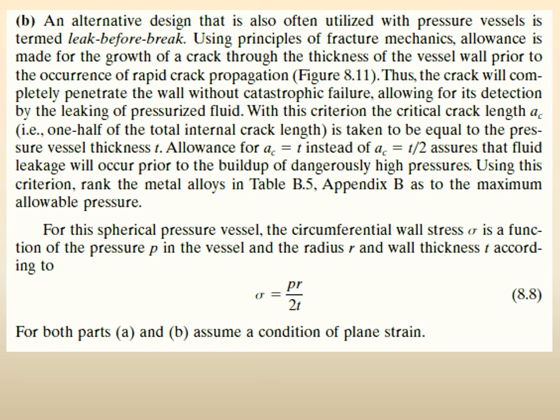There is some currently existing crack. Normally this crack can spread throughout the pressure vessel, and then in the end the whole pressure vessel cracks into 2 pieces, fractures and so on. But rather than spreading throughout the body of the pressure vessel, if this crack starts to grow in the thickness direction, then after some time, whatever thickness it has, 2 millimeter, 3 millimeter, 10 millimeter, if it goes through the thickness, then there will be a hole in the wall.